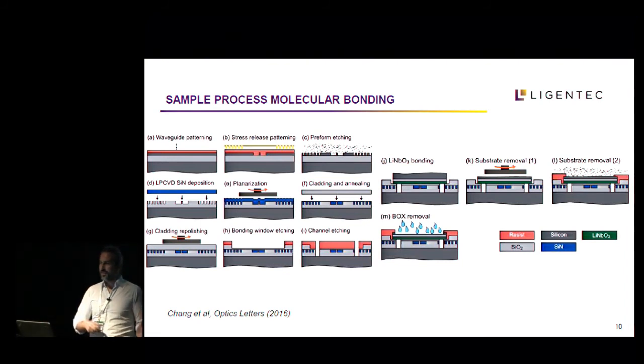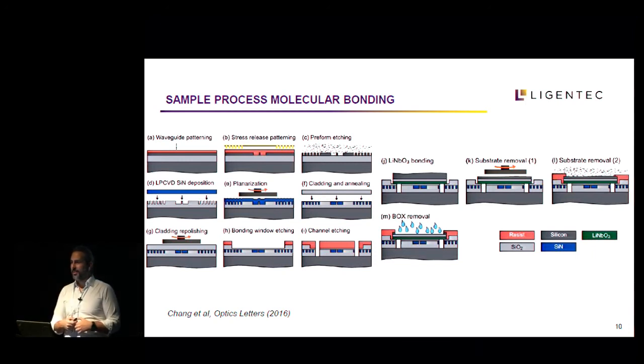So in another part, we take a lithium niobate wafer, and this lithium niobate wafer is properly made to have a thin film of lithium niobate, some oxide, and maybe a silicon handle, and you dice it in an appropriate condition, and then you bond it by thermocompression bonding to this location here, and you can see the channels help take away all the gases generated in the process. But now you have this whole wafer on top and no patterning on the active material. So you need to take away the substrate, so you go to substrate removal, but the substrate is thick, so it is not a trivial process.